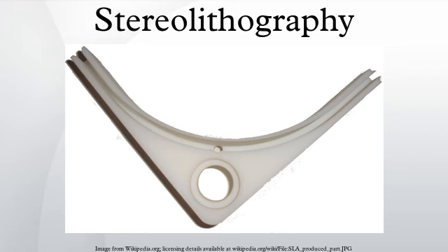After being built, parts are immersed in a chemical bath in order to be cleaned of excess resin and are subsequently cured in an ultraviolet oven. Stereolithography requires the use of supporting structures which serve to attach the part to the elevator platform, prevent deflection due to gravity, and hold the cross-sections in place so that they resist lateral pressure from the recoater blade.